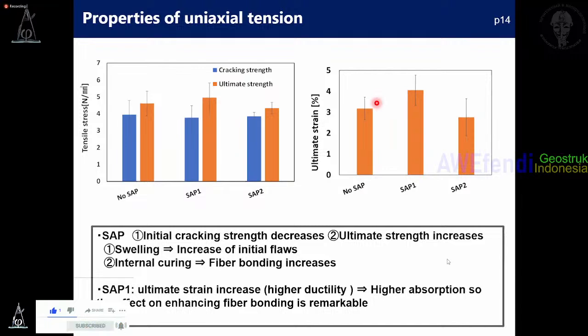So we are considering that initially, because of the swelling of SAPs, you have the initial flaws that may reduce your cracking strength. But later, SAP will release water for further hydration, particularly at the interface of the fiber. So that increases the bonding of the fiber. Particularly if you use SAP 1, you will have the higher absorption, so there is more enhancement of the fiber bonding for the ductility.